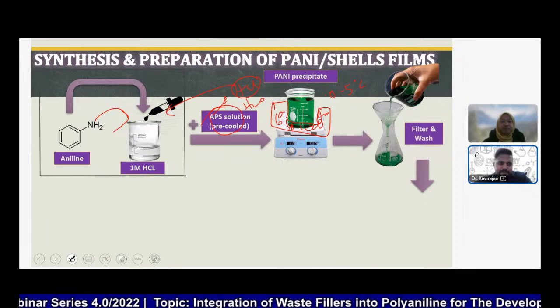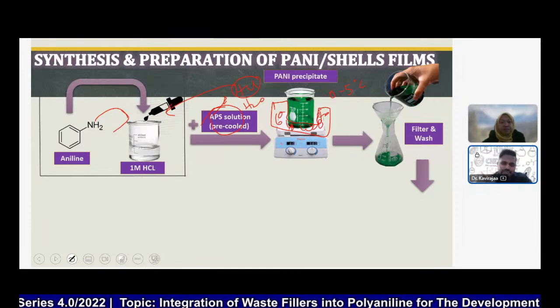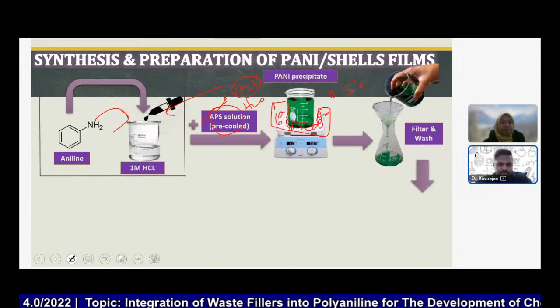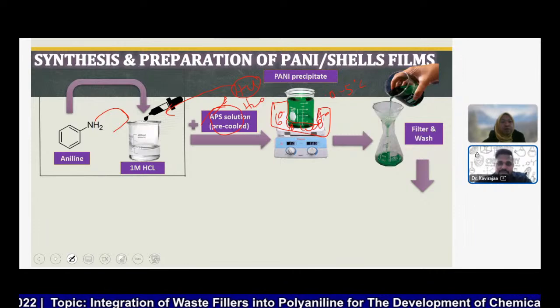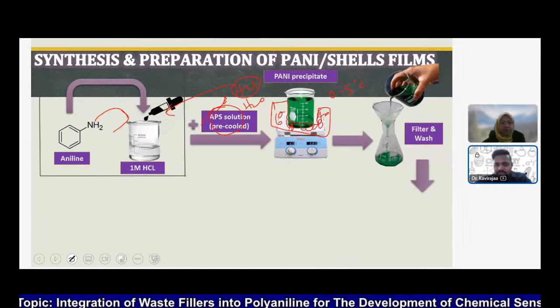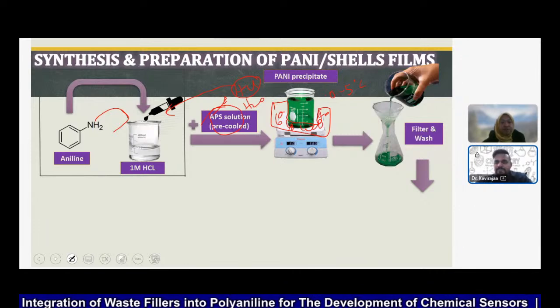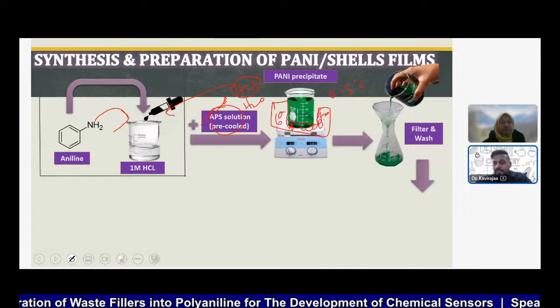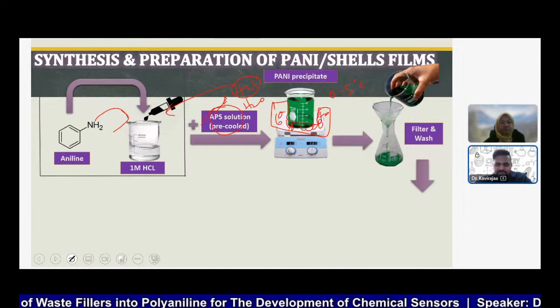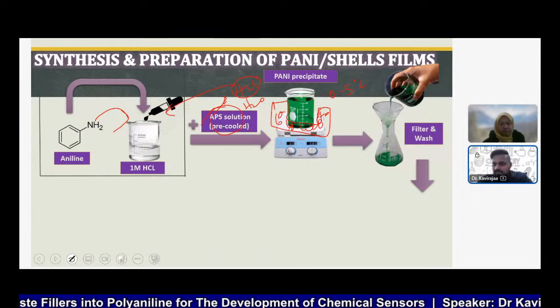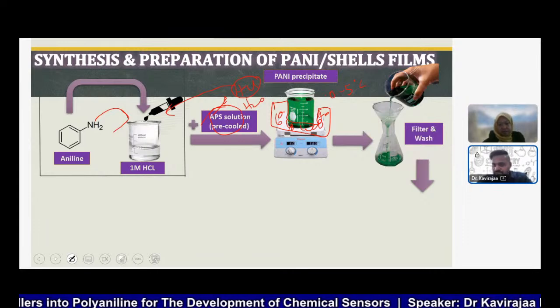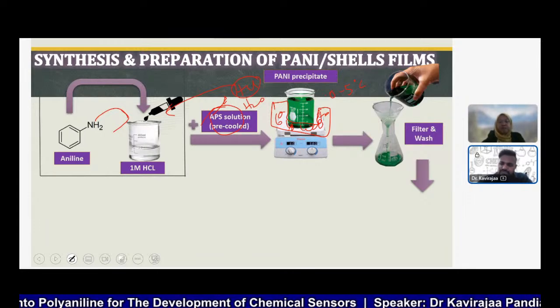At room temperature, the conductivity, the conjugation, everything is out of order because of the elevated temperature. So we don't want the elevated temperature. That's why we will do the polymerization at a very low temperature, which is 0 to 5 degrees Celsius. Okay, and then we will do a normal process, which is filter and wash.